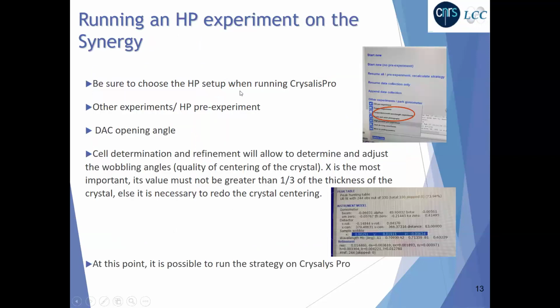The next step is to carry out a pre-experiment to determine the cell and, above all, to fine-tune the crystal centering by checking the wobbling angles. In CrysAlisPro, we will choose the high-pressure setup option as shown here by clicking first Start New, then Experiment, then High-Pressure Pre-Experiment. And at that point, we will indicate the DAC opening angle. Then it's possible to run the pre-experiment and to perform the cell determination.